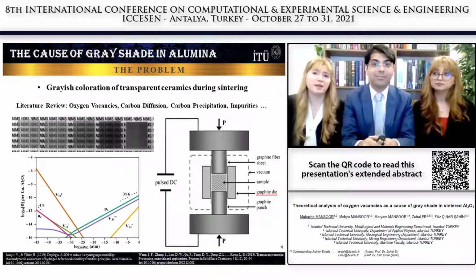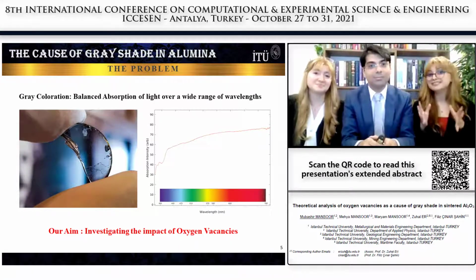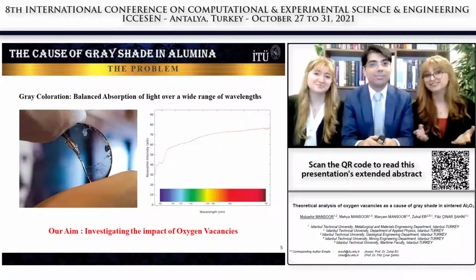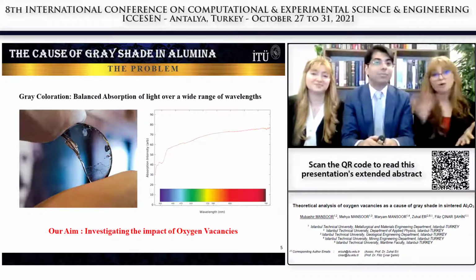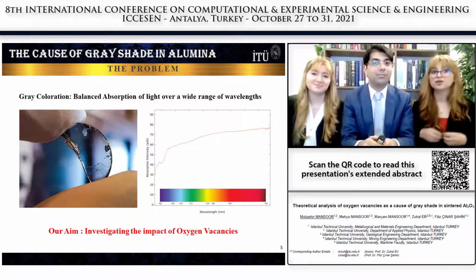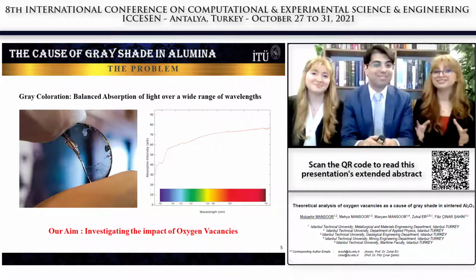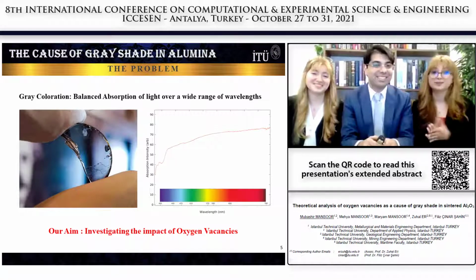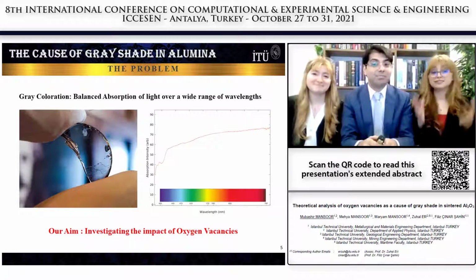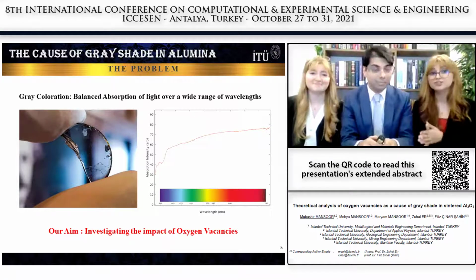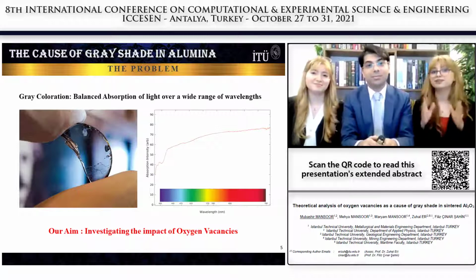So the optical behavior of this point defect requires a very careful investigation. Here is a typical absorption spectra of such ceramics. There is a continuous absorption across all the wavelengths in a balanced manner, which causes the gray shade. So we embarked on a journey to calculate the absorption spectra, which should be expected from oxygen vacancy defects, to see if this experimental spectra can be produced by the theoretical studies on vacancies. If it's not possible to reproduce a similar continuum across the UV-visible spectrum through ab initio calculations, then we can safely refute the oxygen vacancy theory as being the cause of the gray shade.